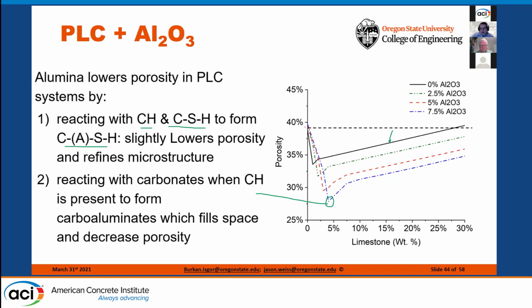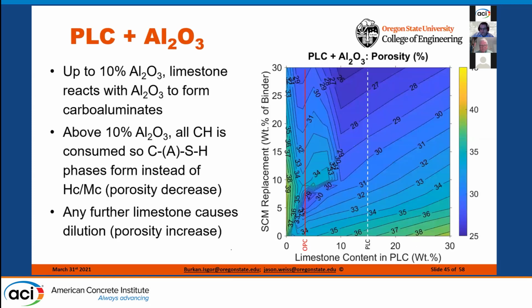The other thing that we notice now is while our 0 line may be here, and we may have seen a similar performance around the 15 to 18% range for our conventional Portland cement systems, now when we start adding slag, we could possibly go to much higher limestone contents where we could really see some of these behaviors improve. If we look at this plot, it gets slightly more interesting than when we looked at the silica system plot, because what you'll notice is, again, at 0, we have about that 39% porosity. But now instead of the contour line marching linearly across the plot, by adding some of the alumina into the system, we really get a trough-type behavior with very low porosities.